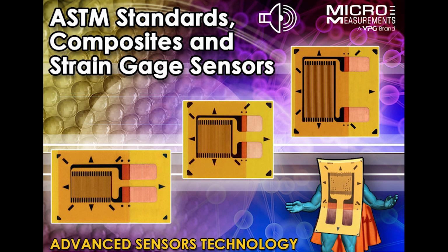We've been doing composites. I've been in the composite industry myself for 25 years now, and pretty much doing testing for the most part of that. So the strain gauging part of it is, as you use it and realize the importance of it, I think right now probably more than half of what we do is strain gauged. And we do all kinds of different tests for mechanical purposes. But the importance to me is, how good is your data? It's usually based on how you're testing it. And the ASTM is really good, the Bible, as far as how you're going to run the test. But there's a little bit of know-how, which gauge sometimes performs better than others in certain situations. And that takes a few years to get around to.